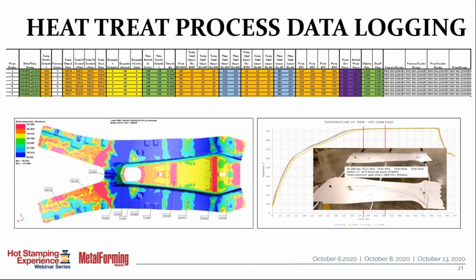So when we build the tool, what we have to do is to take those simulations and determine, are those simulations accurate? Can we correlate to actual results? So we take blanks, we learn how fast we can heat them up by doing thermal traces on blanks with thermocouples. We then use that to set the amount of soak time in the furnace for proper alloying and to establish a minimum temperature or time at a certain temperature in order to properly austenitize, soak, and alloy the material.